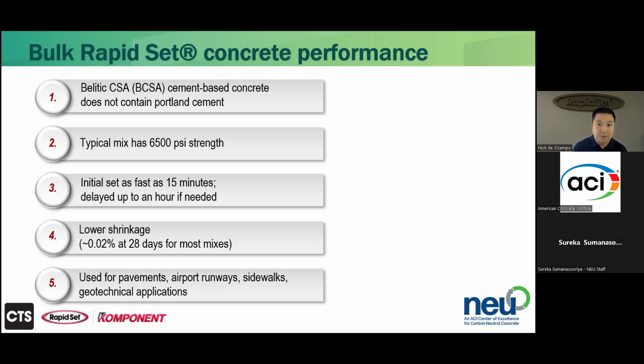With all that said, a typical rapid set concrete mix design is going to have roughly 6,500 psi compressive strength as a design strength. Doesn't mean it can't exceed that, but that's what it's designed for. The initial set can be as fast as 15 minutes, but can be extended, as in the case of the Pacific Northwest, to have an hour of mixing time. The product is expected to be low shrinkage, right around 0.02% at a reasonable water cement ratio. In most applications, it can be used wherever Portland cement is used, so long as crews are ready for the accelerated working times.